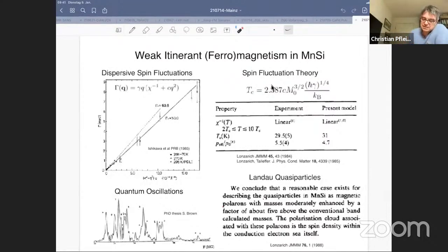And these studies basically extended Stoner theory and introduced the effects of spin fluctuations, and then Lonzarich and Taillefer were the first to be able to calculate the transition temperature correctly out of measurements of the spin fluctuation spectra observed in inelastic neutron spectra.